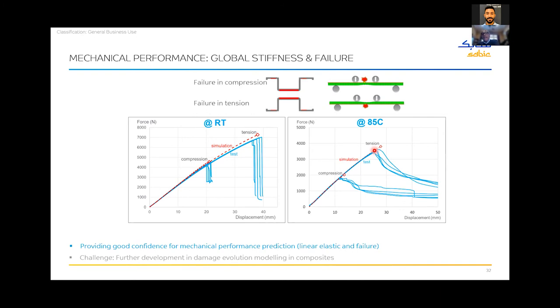Change the problem around to elevated temperature, the problem gets more complex, of course. You can see both in tension and compression, the data is pretty tight. We can still do a pretty good job of the linear elastic physics as well as the onset of failure, but we do a horrible job of predicting everything after that. That area under the curve to the right of this, we're simply not able to capture that energy content at elevated temperature. The reason for that comes down to a deep understanding of the damage mechanics, initiation, propagation, the crosstalk between the different damage, and the heavy amount of viscoelasticity that the resin will bring because it's a thermoplastic.